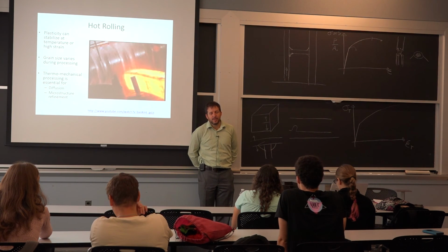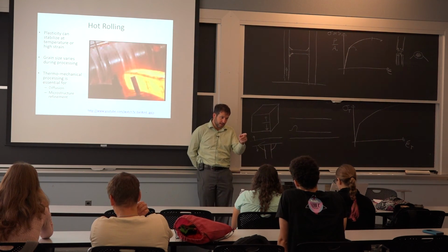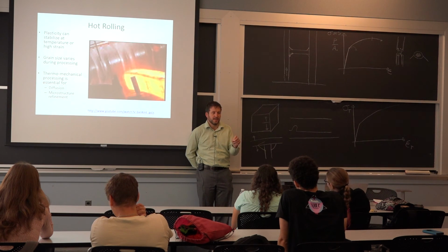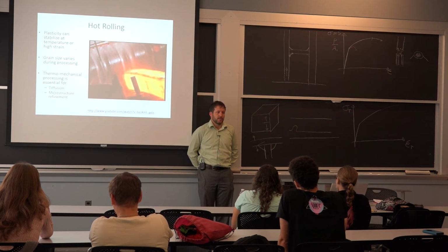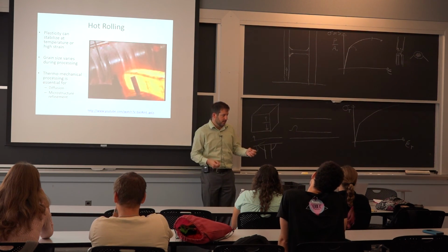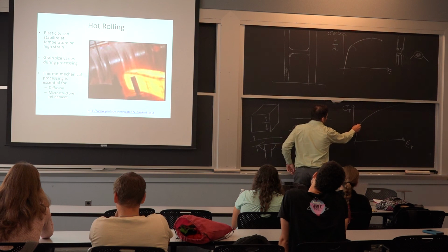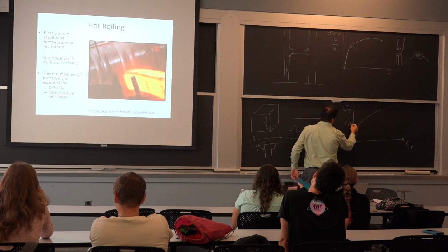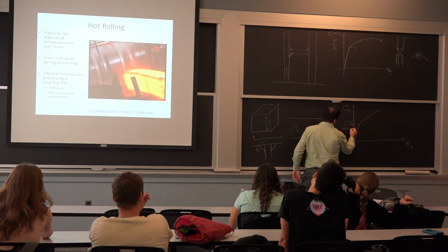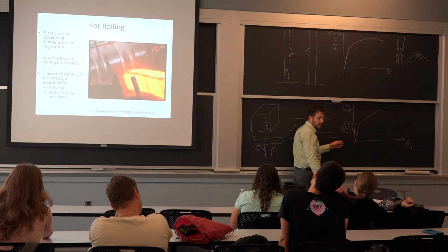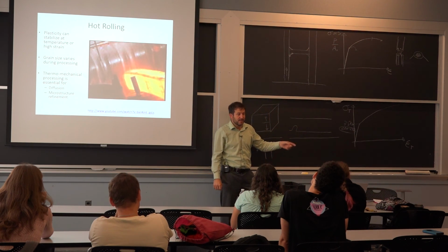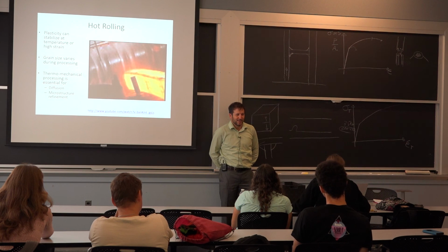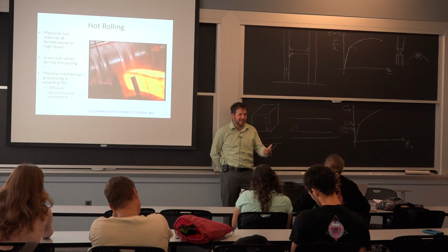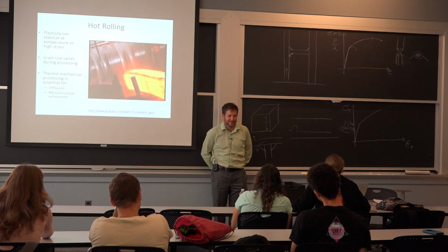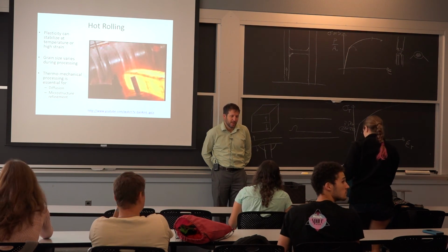I've seen it, so that specific issue of the inclusion being at the center comes up in pre-stressing wires. You take pieces of steel that normally, for our stress strain curve, we're looking at 35 KSI, but you can boost that up to 200 or 250 just by cold working the steel. But when it snaps, it's always at an inclusion. Your strength becomes dependent on how big that inclusion was. That's it.